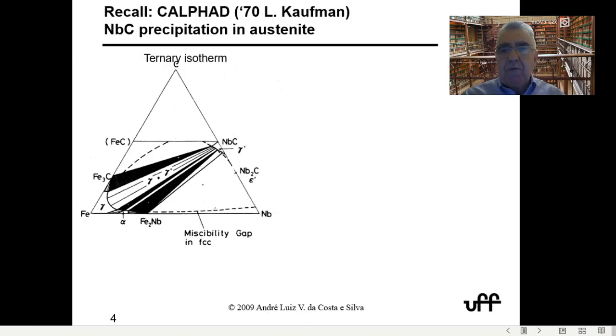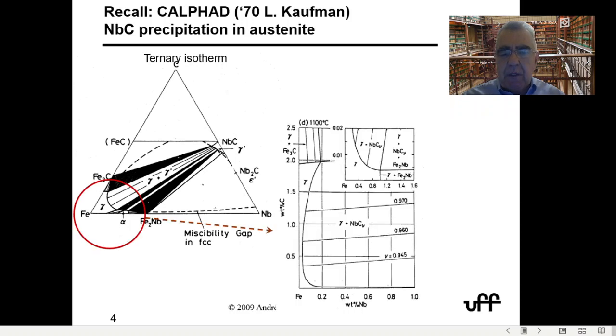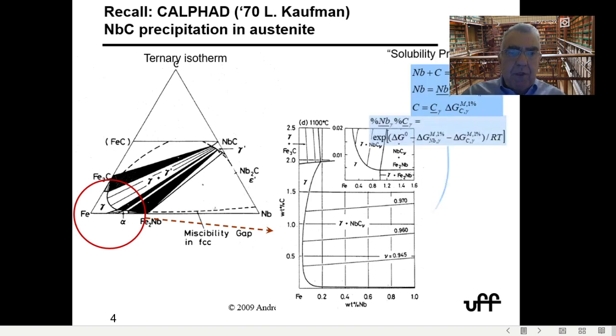And then in the 70s, the CALPHAD method came in. And using this, we could see that the solubility and the miscibilities of the carbides were very similar. And you can use solubility products to get phase diagrams. So this was a big breakthrough, I think, by Larry Kaufman and the CALPHAD people.